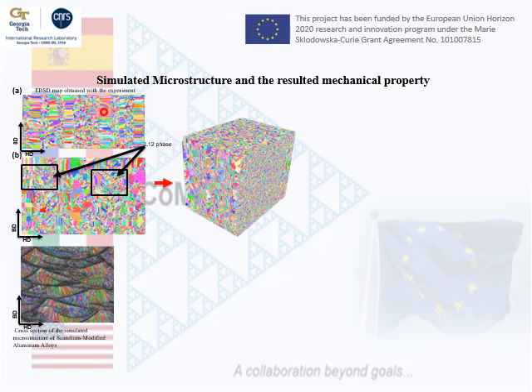We can reproduce the fine grain zones. We can also reproduce the columnar grains. And simply here what we observe is that we are simulating only one part of the process. The reason for this is very simple to understand, right? If we try to simulate the whole volume, it is possible to begin with, but in that case we need to utilize a very fine cell size, which has to be smaller than the smallest grain that we would like to represent in the simulation.